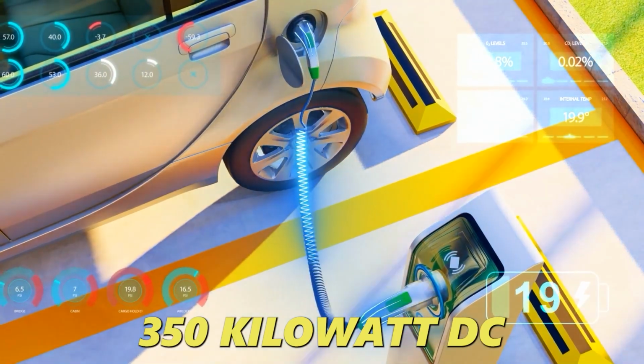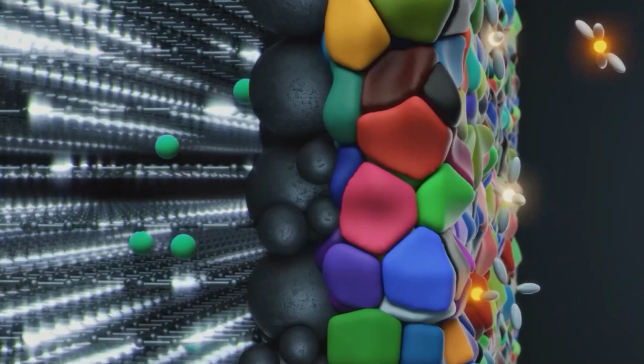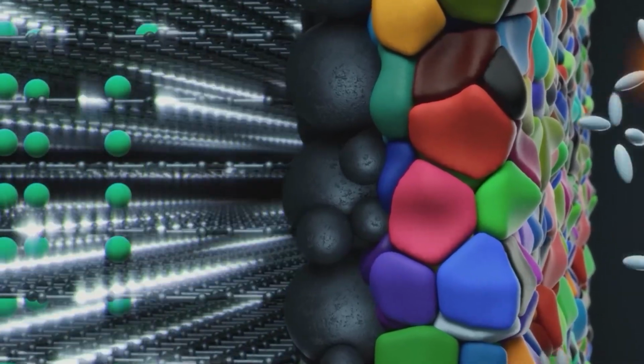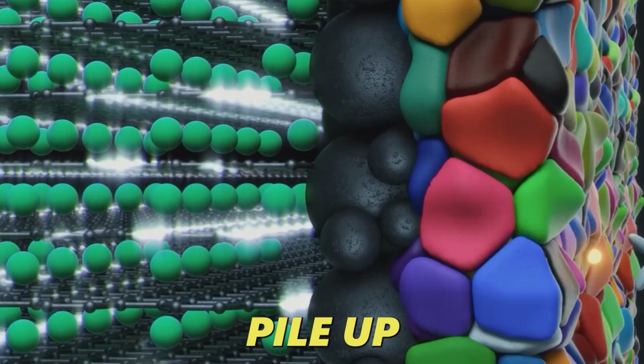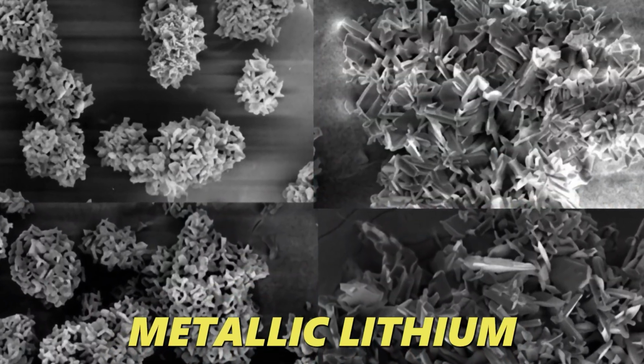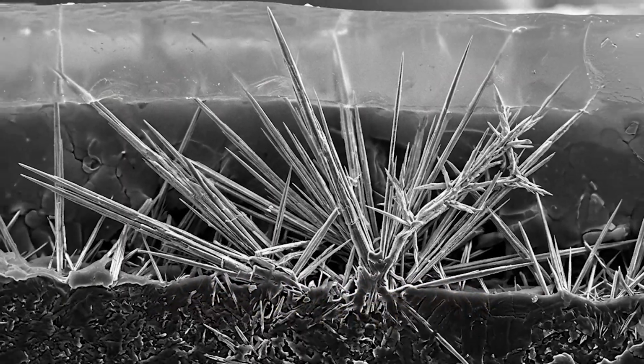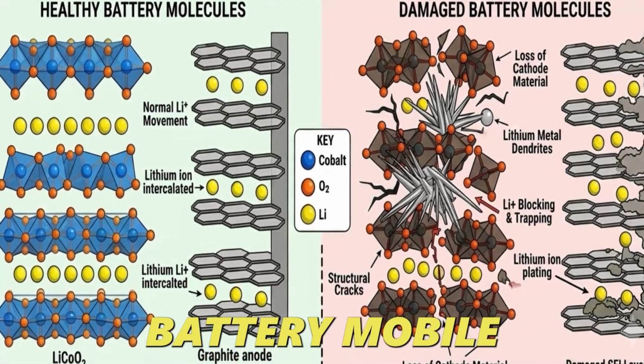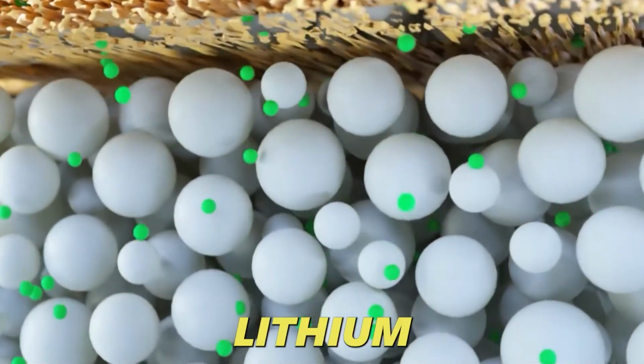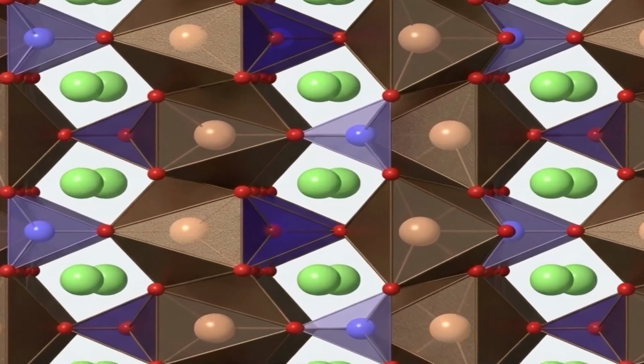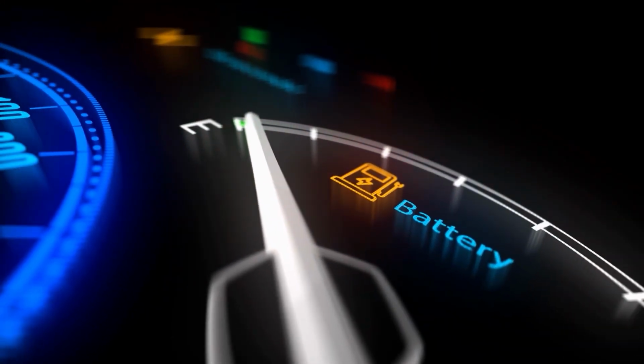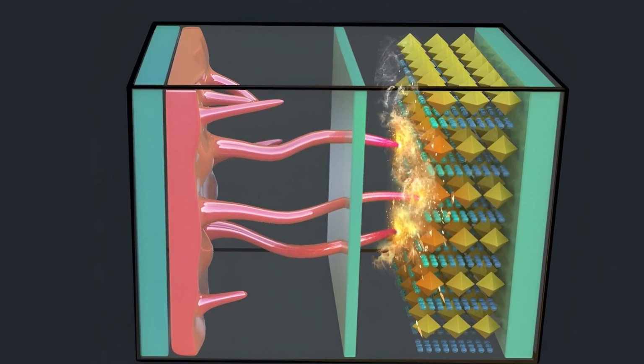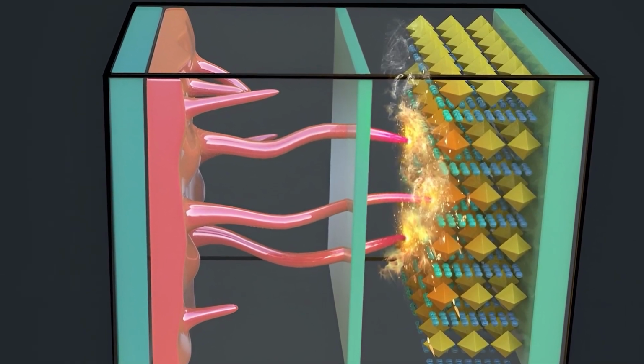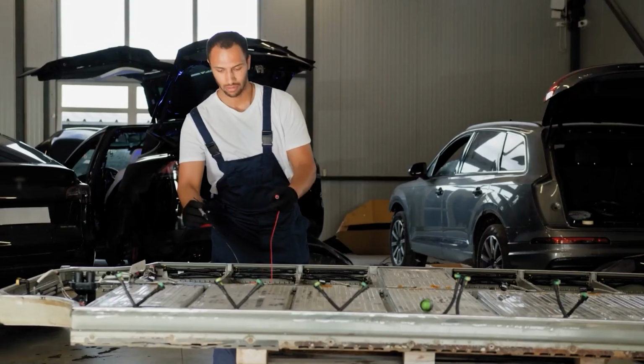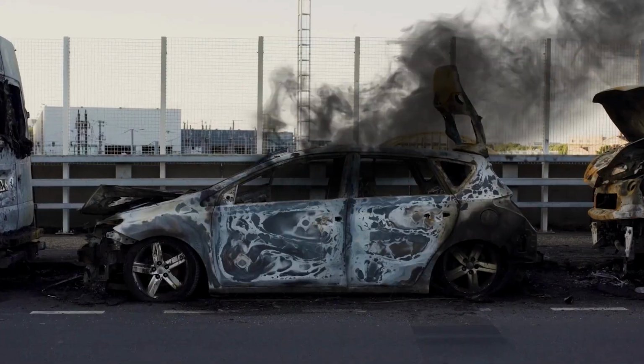Now watch what happens at 350 kilowatt DC fast charging. The ions are being forced into the anode so rapidly that they can't distribute evenly. They pile up. They crystallize. They form these lithium dendrites, needle-shaped metallic lithium deposits. And unlike the lithium that's supposed to be in your battery, mobile, reversible, useful, dendrite lithium is dead. It's trapped. It's contributing zero to your usable capacity. Worse, if a dendrite grows long enough to pierce the separator membrane between the anode and cathode, you get an internal short circuit. At best, that cell is ruined. At worst, and this is rare but real, thermal runaway.